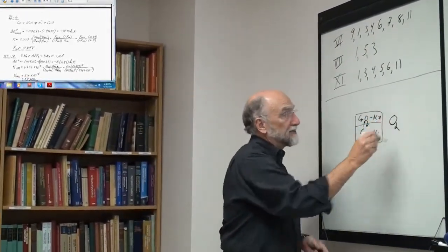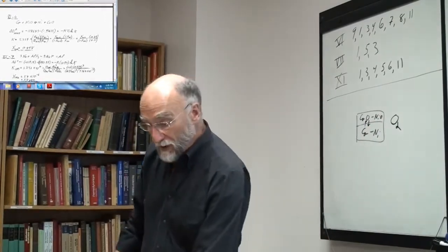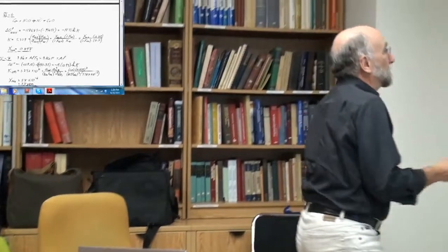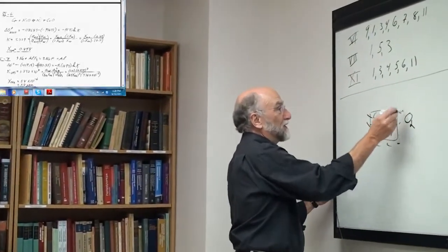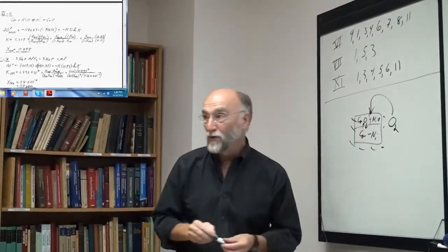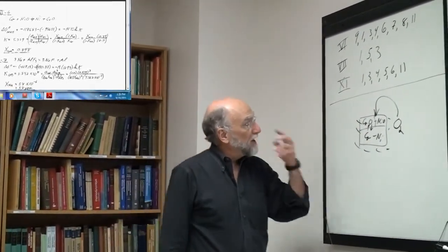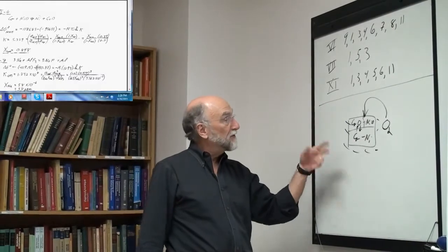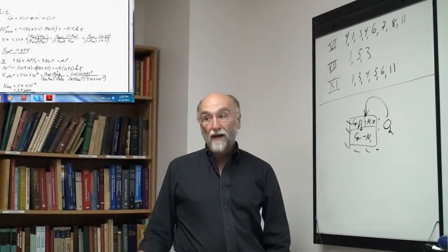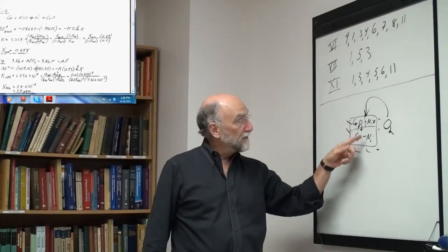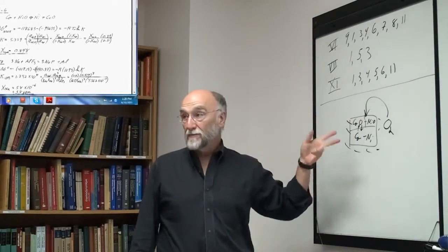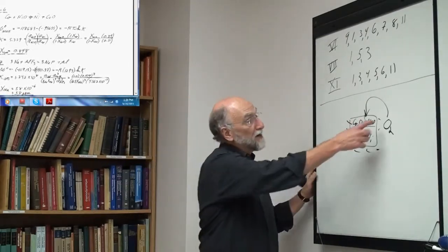There's an oxygen gas out here. Neither phase is at equilibrium with the oxygen gas. The oxygen gas is oxidizing the alloy, and the oxygen gas comes in this way through the pores or something. Okay. But so this is forming. Here you have two solids, but this would be the same thing as if this was a liquid metal and that's a slag. Okay, it's an oxide, a metal phase and a nonmetallic phase containing the same elements. And you're assuming they're not at equilibrium with oxygen.